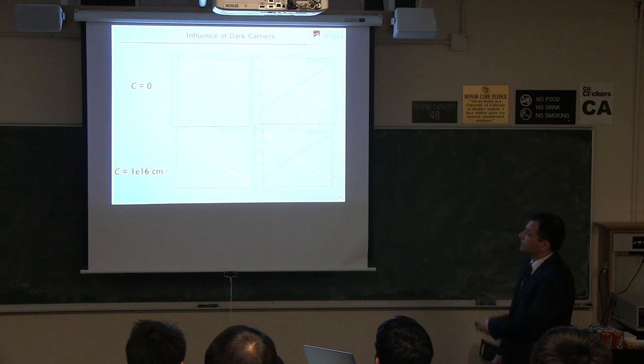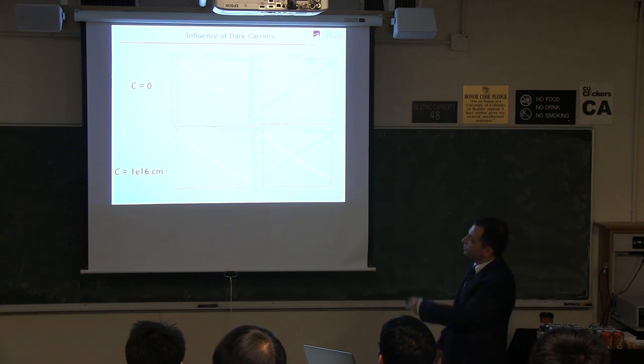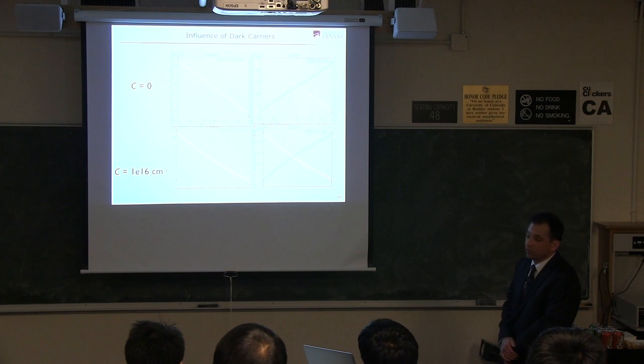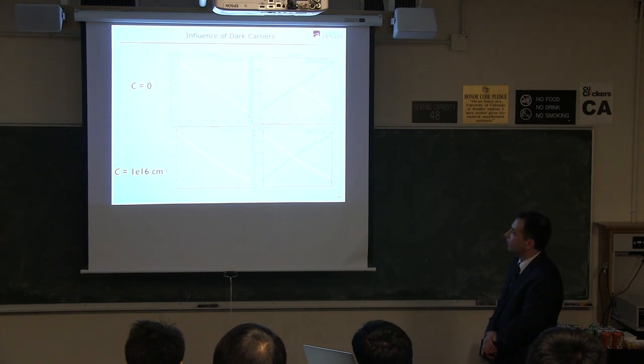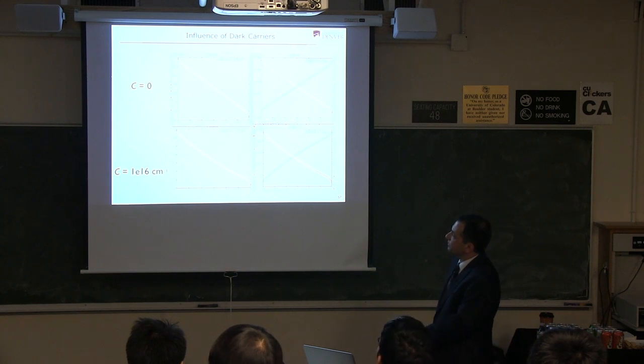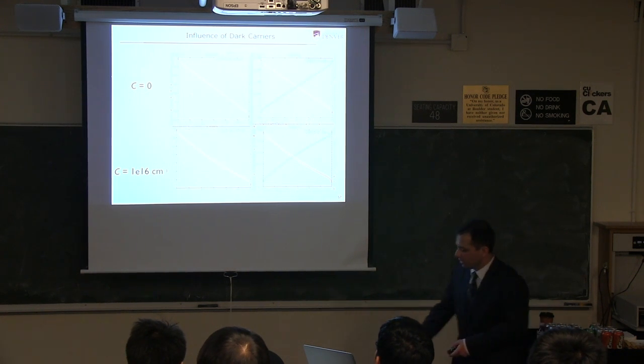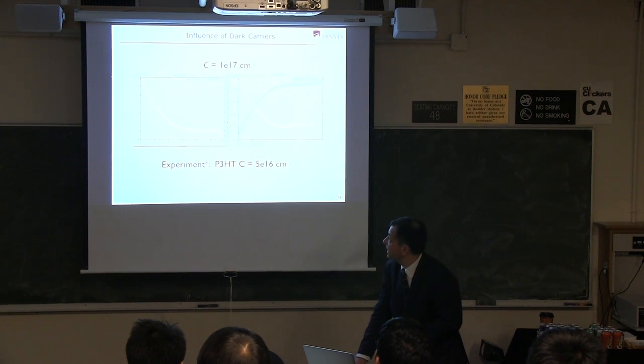So what we can do is model the band structure of the device. This is the electric potential versus position of the device. This is electron and hole densities in the device. And of course, if there are no dark carriers, you have more or less flat bands and a uniform field in the device, so you have a constant derivative of the potential. Now, if you start adding in dark carriers, this number C, you start depleting at one of the electrodes over here, and you get non-uniform fields in the device.